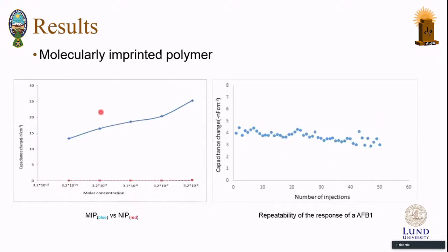In the case of molecularly imprinted polymers, we have one molecularly imprinted polymer, which is synthesized in the presence of aflatoxin, and the non-imprinted polymer that is without the presence of the aflatoxin. We can see that there is no specific interaction, as can be seen in the red line, and the pockets are specific for aflatoxin. In this case, the molecularly imprinted polymer has a repeatable response until 40 cycles, which is really high. So it's a good option to use it for the measurement in a capacitive biosensor.